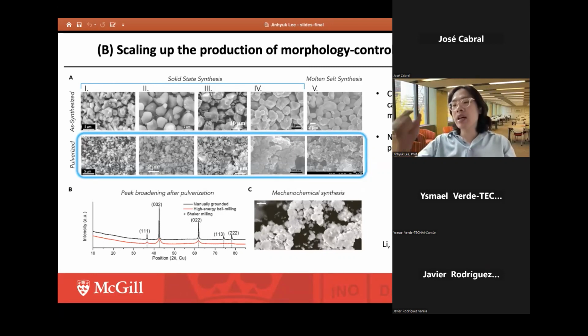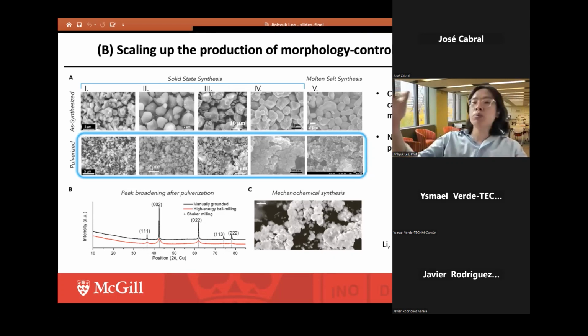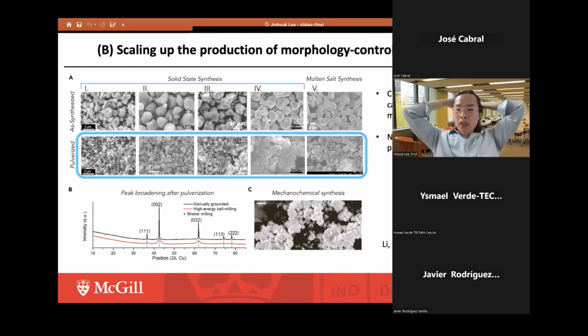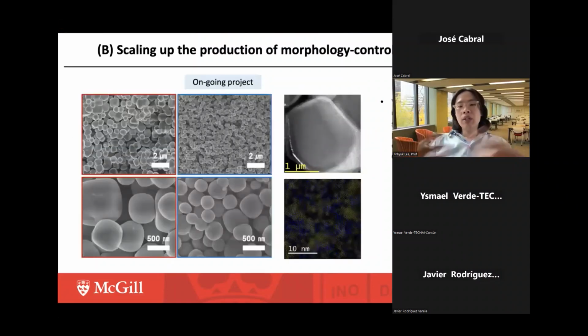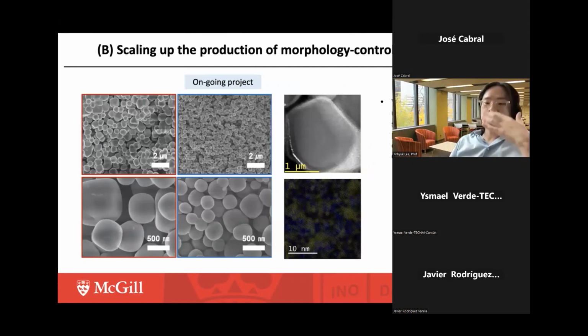You can barely control the morphology, so you cannot apply a uniform coating, and the exposed particle surface can also greatly expedite this capacity loss. So we need to come up with new synthesis and processing methods to produce more morphology-controlled DRX particles. So at McGill, we are currently developing a universally applicable DRX synthesis method to address this issue.